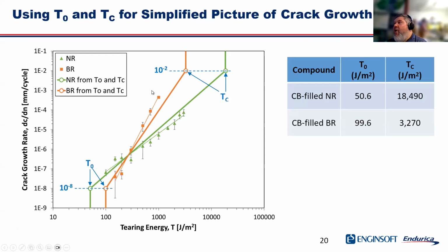And we can use that principle to make rapid estimates of the crack growth rate behavior. So what I'm doing here is I'm overlaying in this slide the results of the 20-hour crack growth test, right? The triangle data points here and the square data points here. That's the 20-hour crack growth test, and you can see you get a certain power law slope. And what I'm going to do then is take the measured T naught and TC values for these two materials, and for T naught, I'm going to plot those at a crack growth rate of 10 to the minus 8 millimeters per cycle, right? So you can see here T naught for the natural is about 50 joule per meter squared. For the BR, it's about 100 joule per meter squared. So you have these. And then if I plot the TC value at a crack growth rate at 0.01 millimeter per cycle, then you get this reversal in ranking.